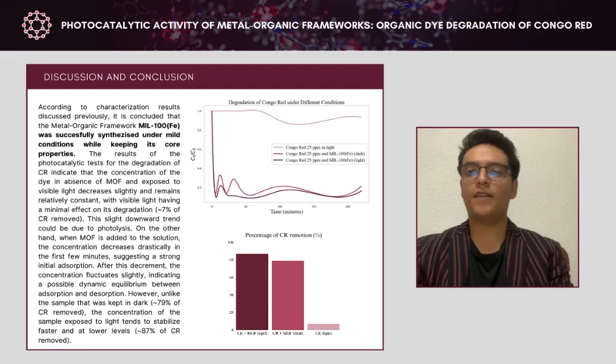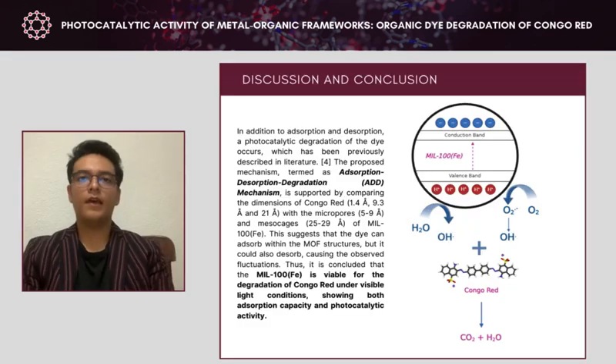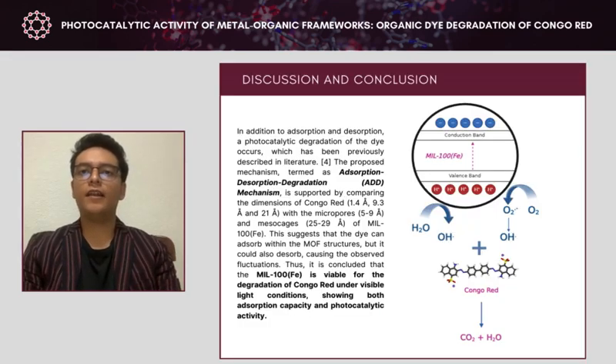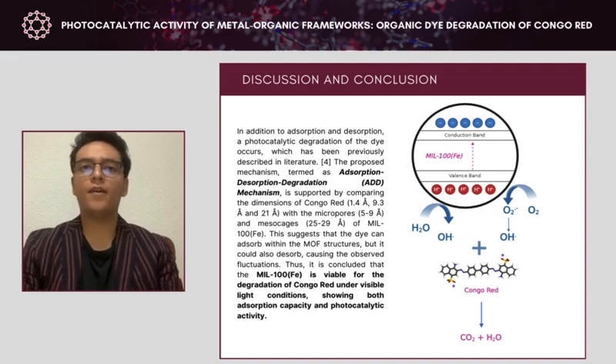However, unlike the sample that was kept in the dark, from which 79% of Congo Red was removed, the concentration of the sample exposed to light tends to stabilize faster and at lower levels. 87% of Congo Red was removed at the end of the experiment. In addition to adsorption and desorption, a photocatalytic degradation of the dye occurs, which has been previously described in literature. The proposed mechanism, termed the adsorption-desorption degradation, ADD mechanism, is supported by comparing the dimensions of Congo Red with the micropores from 5 to 9 angstroms and mesocages from 25 to 29 angstroms of Mesoporous iron 3 carboxylate. This suggests that the dye can adsorb within the MOF structures, but it could also desorb, causing the observed fluctuations. Then the degradation mechanism occurs.